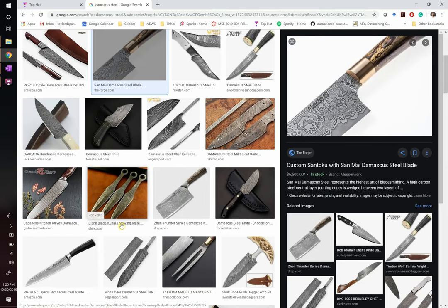The way that you make that is you take a bunch of metal, leaf springs or whatever you want to make it out of, right? You pile them up on top of one another. You clean them first. You weld them together so the edges are all welded together, and then you start pounding that thing. As you pound it, there's literally big layers between it. So that's not the same as a grain boundary, because each metal itself is filled with billions of grain boundaries. Instead, those lines you're seeing are the layers between your big sheets of metal, which probably includes surface impurities, like a little bit of oxide. So that's what you're seeing there, the surfaces between those.